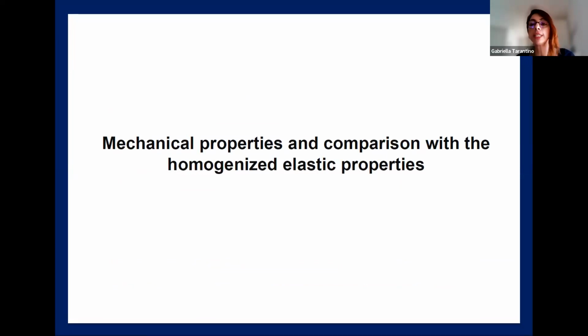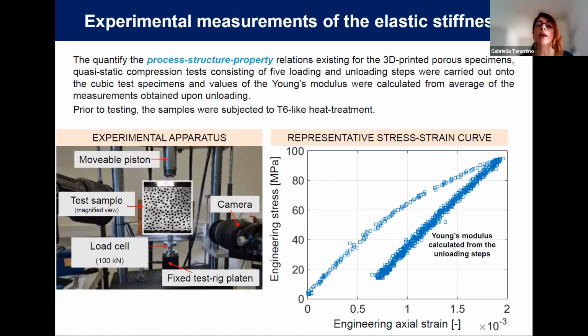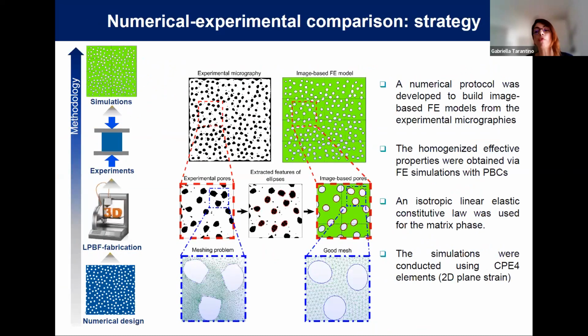What I'm going to present you there is just a summary of the results, where we estimated the elastic stiffness. A part of our work currently also concerns the elastoplastic damage of this material. Now, to measure this 3D printed model, we used standard compression testing, and since our post-treatment has revealed that the material contains a negligible percentage of defects, we carried out a uniaxial quasi-static compression test with several steps of loading and unloading cycles, and we estimated the measured elastic property from the unloading step. That's pretty standard, but in order to follow our strategy, which goes from the design to the fabrication and to the experiment, we needed a stable predictive model for this material.